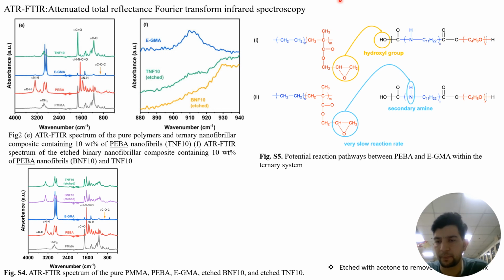Notably, the amide group, the NH group in the PEBA here, the bending vibration peak of PEBA is initially located at around 1555, but due to a red shift, it shifted to 1544 in the polymer composite, in the spectrum of TNF10.